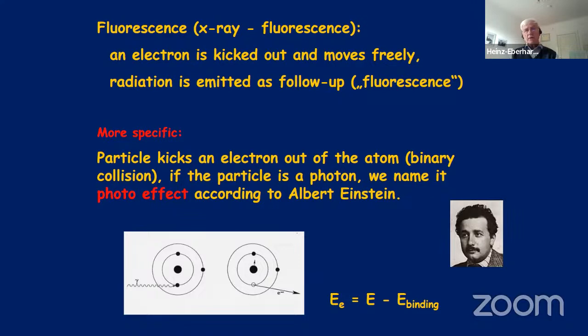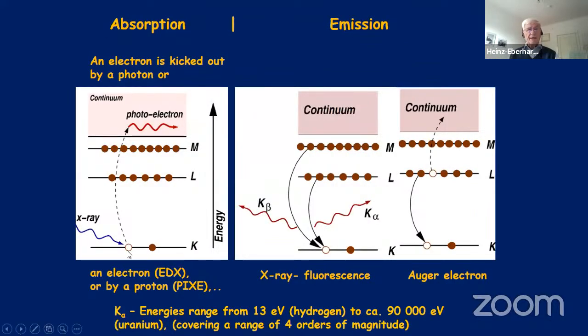When you kick out the electron, the energy stream, you then replace the vacancy by filling in from another electron, from the lower bound electrons, and you get either the fluorescence X-ray emission, or as an alternative, the Auger electron emission. One has to take into account the competition between radiation coming out, the X-rays, or an electron coming out. And due to the scaling of the energies, we have the full range from 13 electron volt up to 90,000 electron volts in the case of uranium.